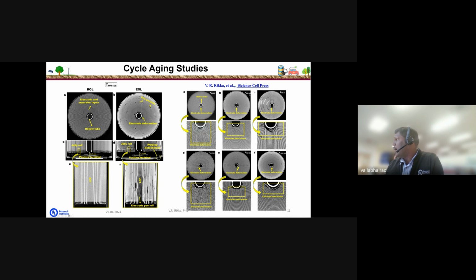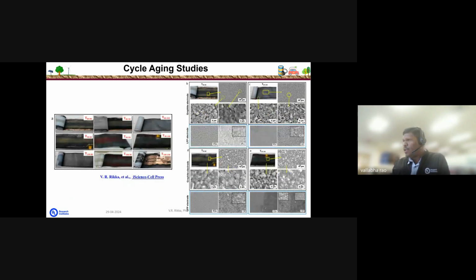We can look at 80 SOC and 100 DOD. The deformation is less compared with all other test conditions. Whereas for the partial charge with partial discharge, we expected this to have the highest cycle life, but it shows significant deformation in comparison with the partial charge with full discharge, which showed the highest cycle life. So these results are quite controversial with each other. That's what we are trying to identify: what kind of electrochemical aging mechanisms took place over the cycles. For which we carried out failure mode analysis. We dismantled the cells after doing the non-destructive studies, and we identified that in all cells the anode morphology or anode structure was changed.